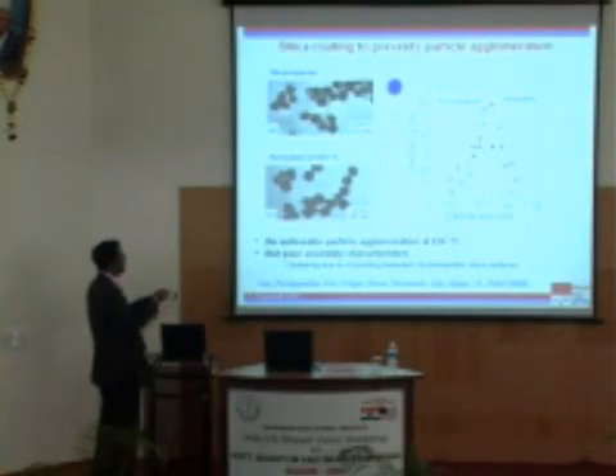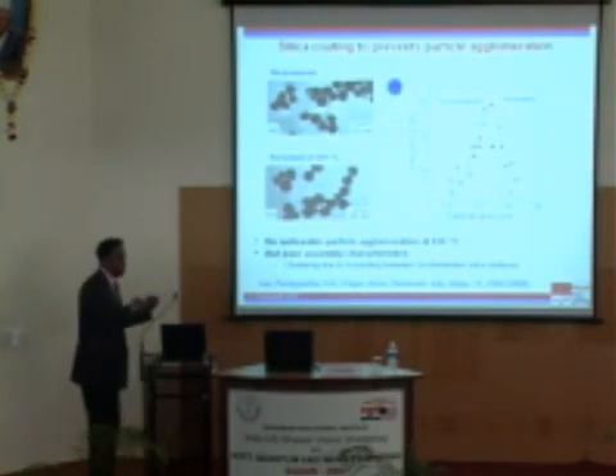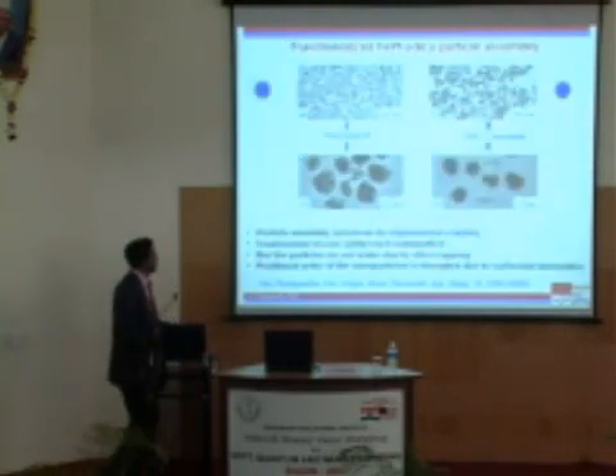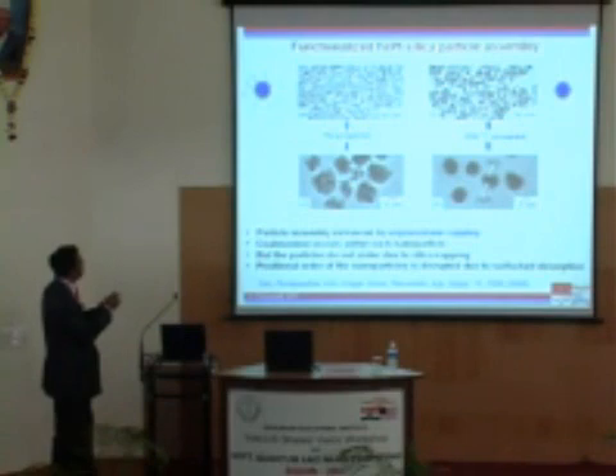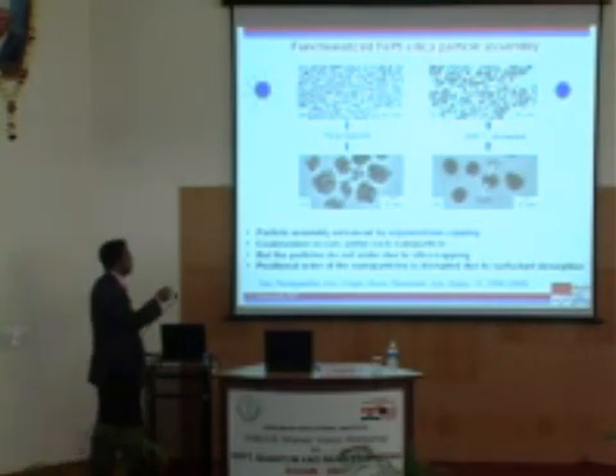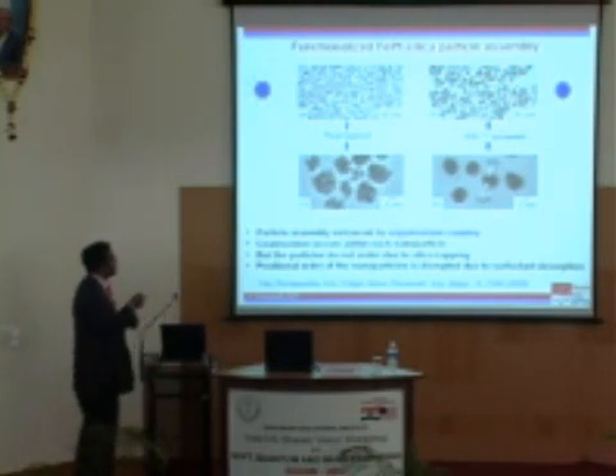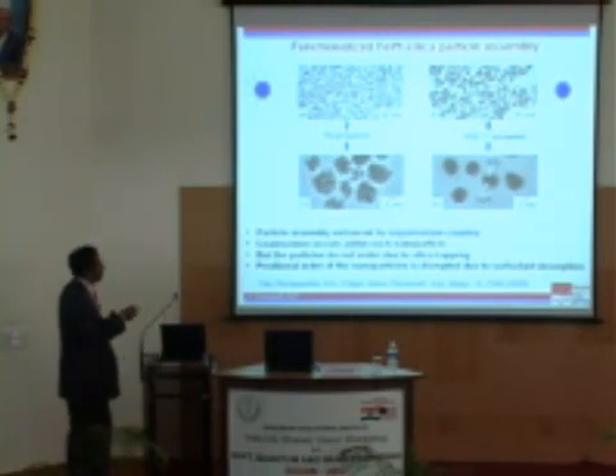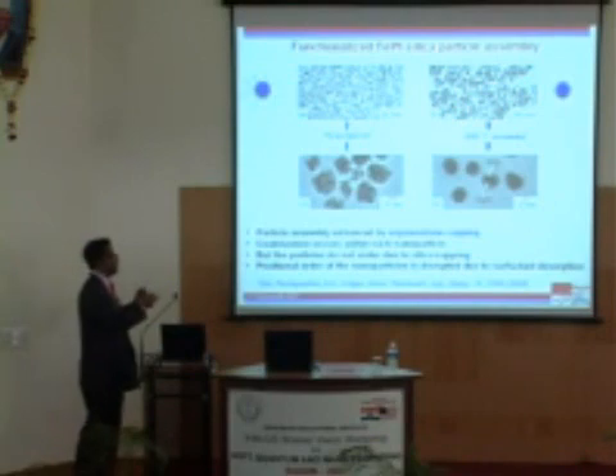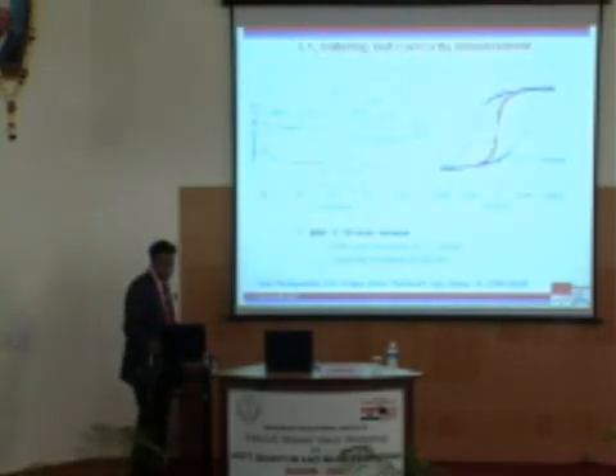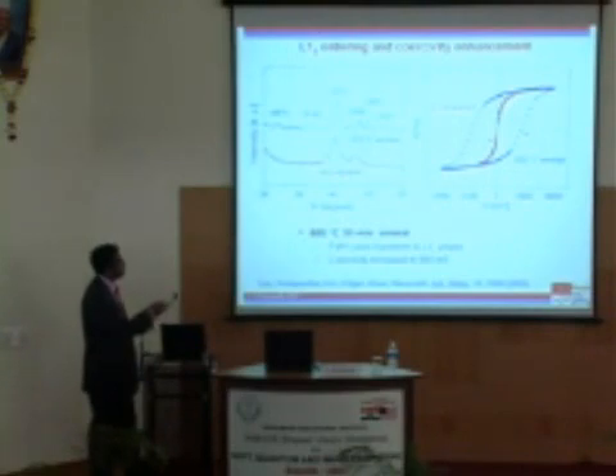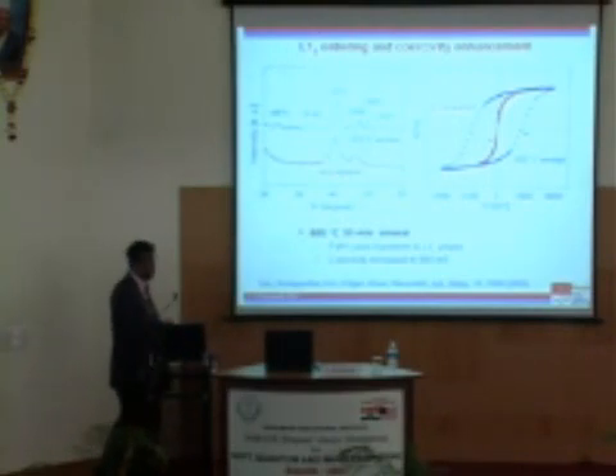And the reason for that is because in silica, you have this OH group sticking out, and those tend to form hydrogen bonds. So you need to functionalize the surface. So we put in a molecule, and once you put the molecule, you can see you get a much better assembly. And once you heat it up, you actually destroy the assembly. But you can reassemble them, of course, by redispersing and so forth. The beauty here is you have, for the first time, after annealing, nanoparticles that are high coercivity and in the nanoparticle shape, where the shape is not destroyed. And that is seen over here. You can see that you get the high coercivity shown by the blue coercivity curve, and the red one, which is the as prepared case, is superparamagnetic.